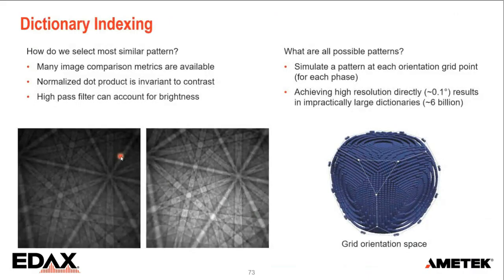Now, when we want to do a dictionary indexing, that means that we want to compare an experimental pattern against a simulated one. How do we select what pattern is the same? What we've implemented here is a normalized dot product. So we just take a pattern, look at the individual lines in there, let's say, in the image, so not the bands, but just the columns and rows, compare that against the simulation and see what works best.